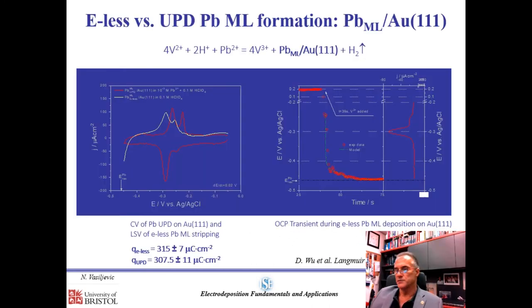There's a new phenomenon that has been researched in the last few years, which is electroless monolayer deposition. So basically, this is electroless deposition, but it's not a bulk formation, it's just a monolayer. It's been reported so far for lead, and pretty much occurs on every substrate where lead makes underpotential deposition. So it's very simple in terms of the properties of the electroless lead monolayer and UPD lead monolayer. When we look at the stripping characteristics of the electroless and UPD lead monolayer, we see that in terms of thermodynamics and shape of the stripping, they are quite similar.